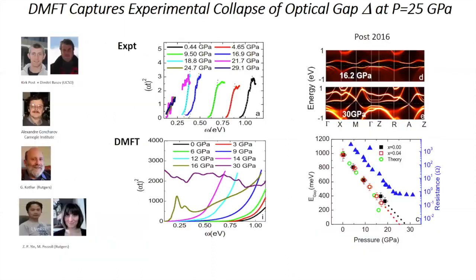So the next thing that we did is that we looked at a spectroscopic property, and that's going to be the optical conductivity. And these are experiments that were carried out by Dmitry Basov's group. The measurements were carried out as a function of pressure that we would hope would suppress both the magnetic order as well as the gap in this material. So if you look at these data, what I have plotted here at the top are the experimental results. This is actually not the optical conductivity, but its inverse. And the black curve on the right is at low pressure.